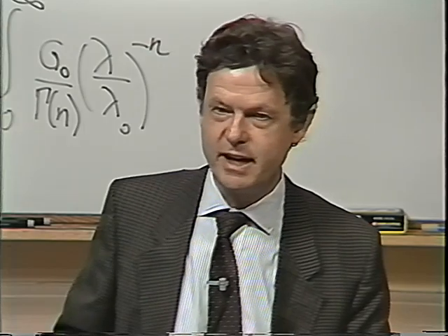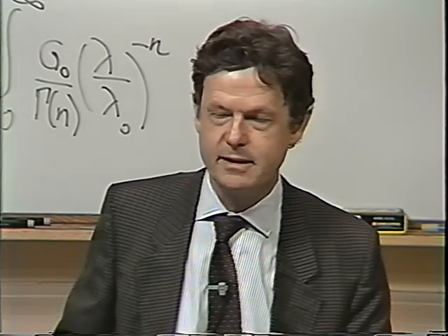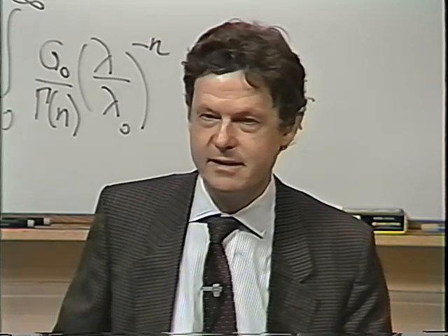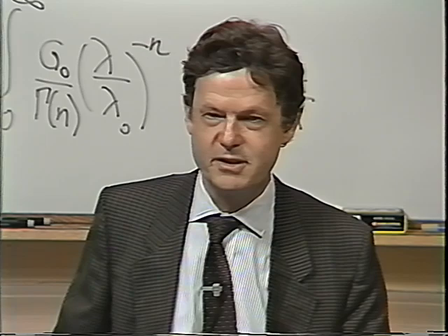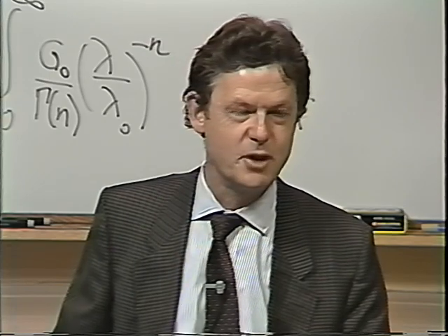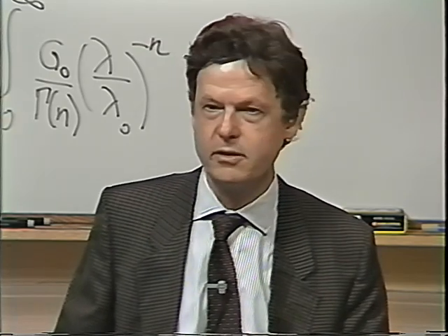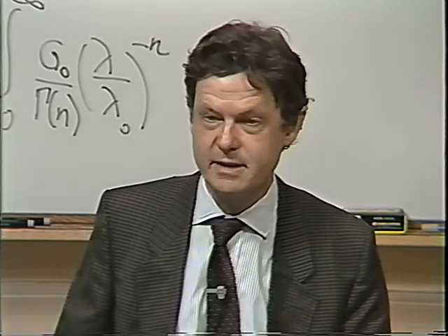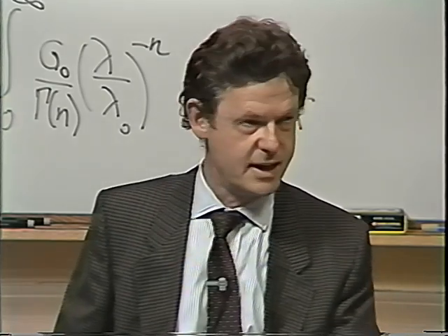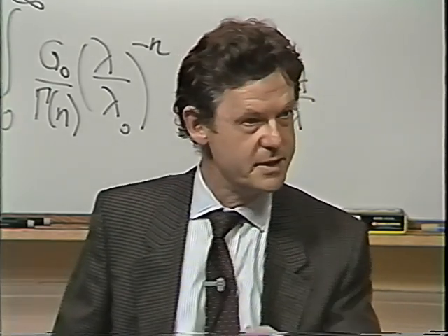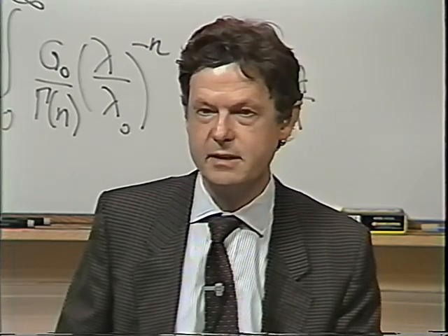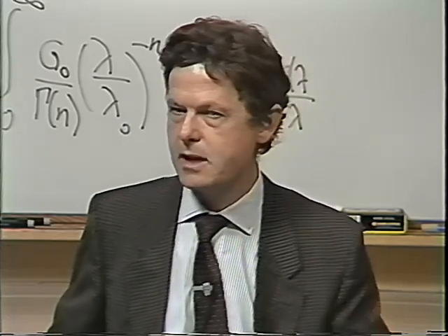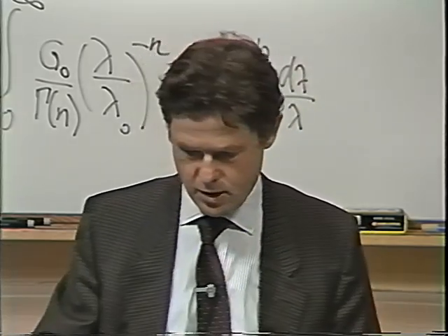In the beginning, I often had the question, what happens to your gel at very short times? And the answer is, to the gel, you have the same thing happening as you know will be happening to a liquid. If you put a very short-term load on a liquid, it behaves glassy. And if you put a very short-time, impulse-type load on a solid, it also behaves glassy. So it's the material in between, the gel, has exactly the same transition at very short times. So there's no difference.